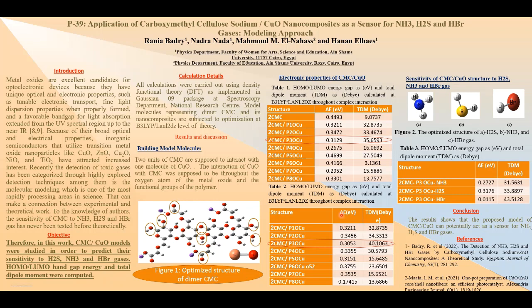By comparison, these two tables show that the most probable interaction mechanism is the adsorption interaction, as it has the lowest HOMO-LUMO band gap energy, which means it is the most probable interaction to occur. Additionally, the sensitivity of the proposed structures of CMC and copper oxide to the H2S, NH3, and HBr gases is also studied in terms of the total dipole moment and HOMO-LUMO band gap energy as presented in Table 3, as the reactivity of the different structures is closely related to the band gap energy between their HOMO and LUMO orbitals.